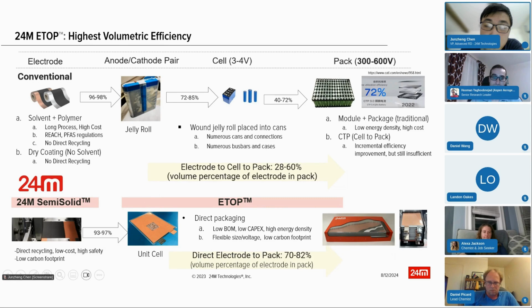And then we do the series connections within this whole pack structure to eliminate any jumpers at all from this pack manufacturing. Then the electrode level of these cells is really, really high energy density in various formats. Then there is a reduction of BOM cost and CapEx assembly, because the pack manufacturing becomes a cell manufacturing, and then very high energy density, of course. And for semi-solid nature, you don't have an electrolyte injection step. You can do whatever size, however big you can be with this unit cell structure. There is no physical limitation of electrode casting on the cell assembly process.